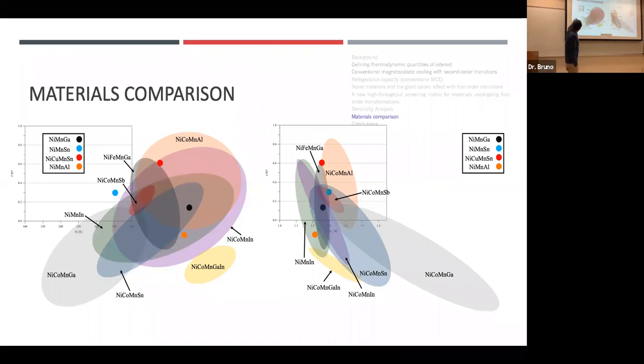But I was able to plot the CRP as a function of MF temperature, which is my hot temperature reservoir for my thermodynamic cycle. And we did this for nickel, cobalt, manganese, gallium, nickel, cobalt, manganese, tin, indium, aluminum. And surprisingly, I found that nickel, cobalt, manganese, aluminum gives some of the largest CRPs out of all of these materials, and I've never studied this composition before. So I think I should.